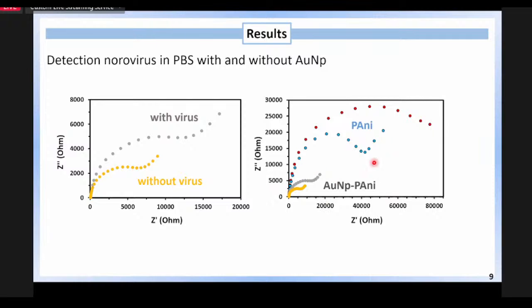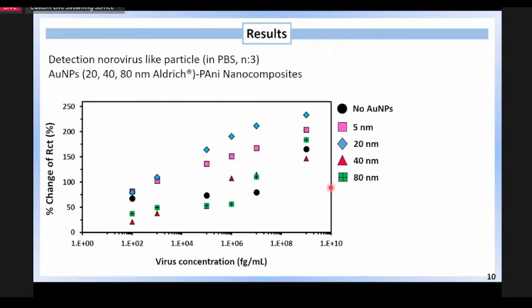While here, the small one below is the polyaniline and gold nanoparticle nanocomposite, which has a significantly smaller radius of the impedance, indicating that gold nanoparticle is indeed very important for improving the conductivity of the sensor. Then I'm trying to make a calibration curve, and checking what happens if we change the gold nanoparticle size in response to the virus detection. And as you can see here, I'm also checking the nanocomposite without any gold nanoparticle, and there is